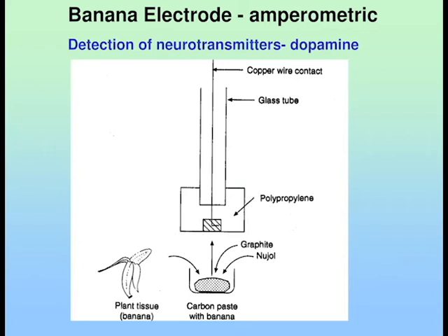Then I keep adding a bit. There's usually an optimum ratio. There's a formula for it. It all gels very nicely, all the graphite powder is in contact, good conductivity, correct? Now I'm a bit greedy and measure a bit too much oil. Oil is non-conductive, so resistance increases again. You get back the same problem.